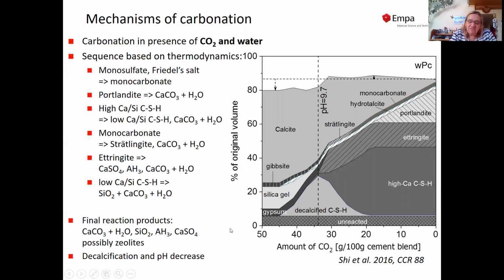If we now look at the effect of adding CO2, or basically exposing it to atmosphere with atmospheric CO2 composition, we predict the destabilization of portlandite to calcium carbonate, followed by the decalcification of CSH, from high calcium to low calcium CSH. We also predict the decomposition of ettringite to gypsum, silica gel, and aluminium hydroxide, as well as, somewhere in between, a destabilization of the AFM phases, monocarbonate to stratlingite.